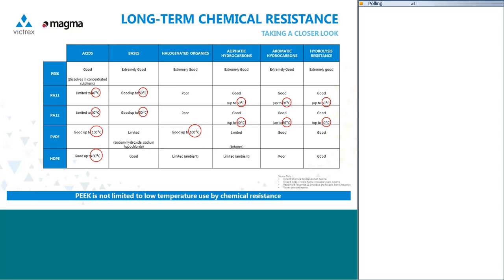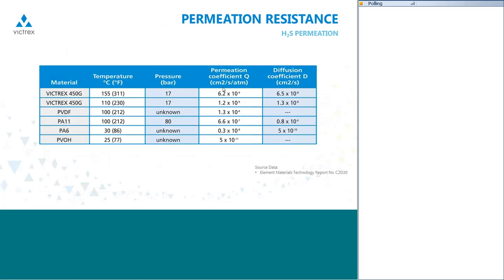So long-term chemical resistance, and by that I mean many, many thousands of hours of test data to support it, PEEK really does excel in that area. And of course, it's not just all about pure chemical resistance. Permeation resistance here, we're talking about H2S permeation. I just draw your attention to a few numbers around the center of this table. PEEK is generally something between 30 and 100 times better than the next best competitor, and we have measured that not only for H2S but also for methanol permeation.